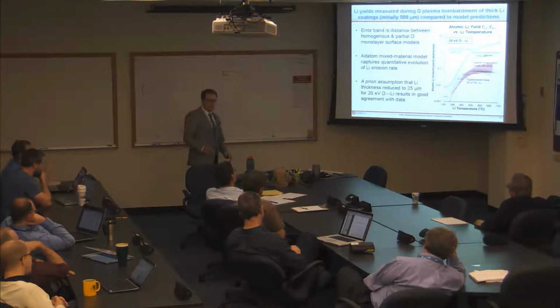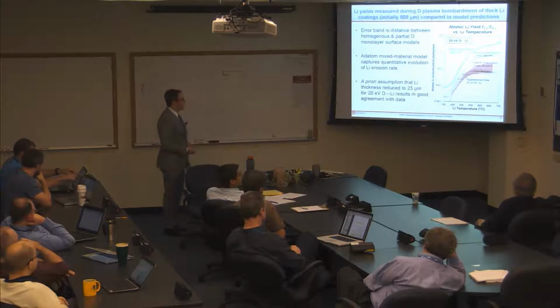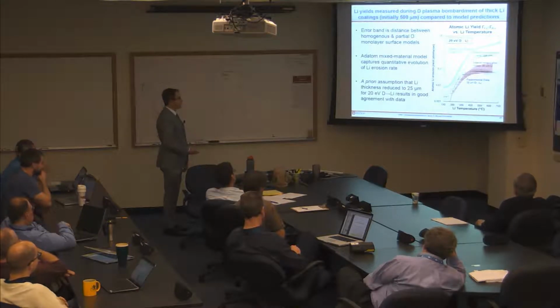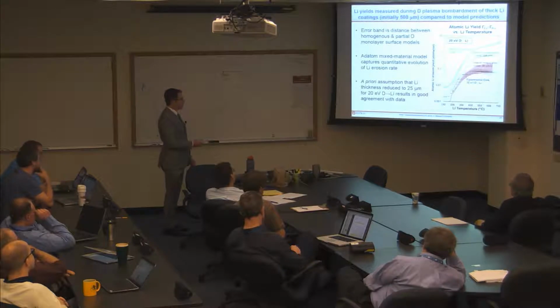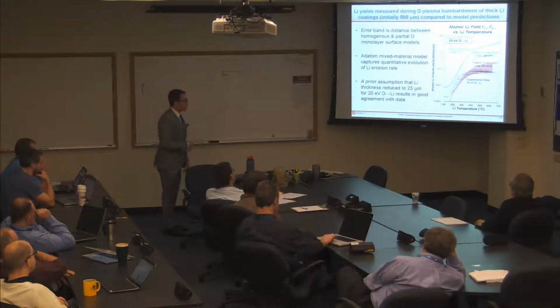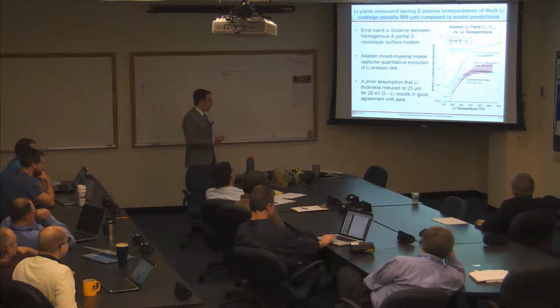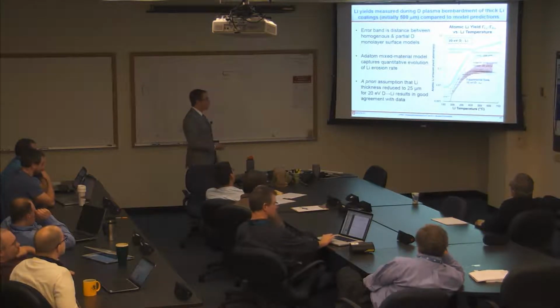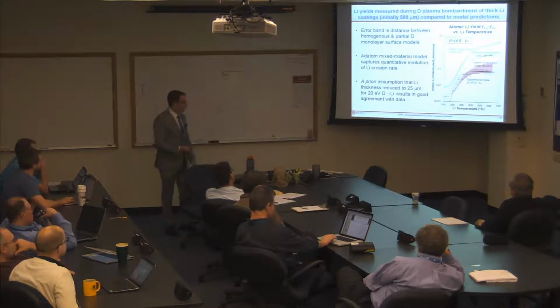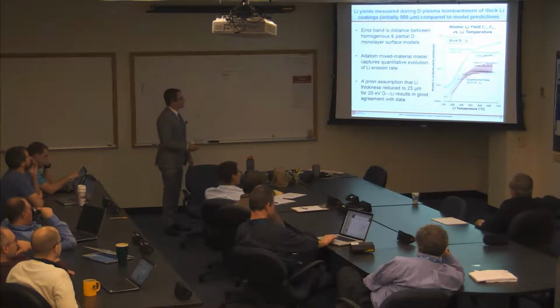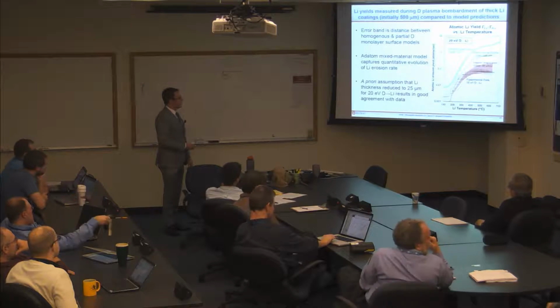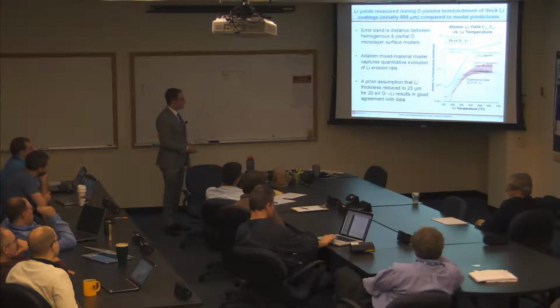Okay, what about the deuterium case? So this is the atomic lithium erosion yield measured during deuterium plasma bombardment. This was one of these initially 500 micron layers that I told you about before, but then you seem to get thinning via melt motion and droplet ejection to some smaller value. And the smaller value that seemed to fit best with the data was 25 microns.